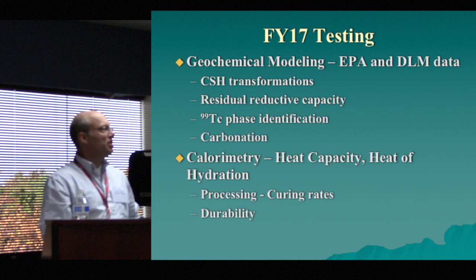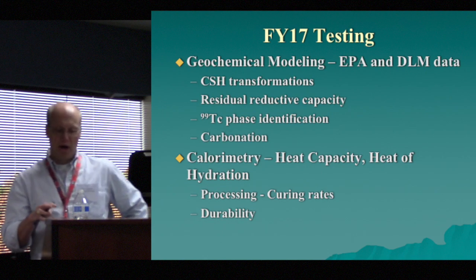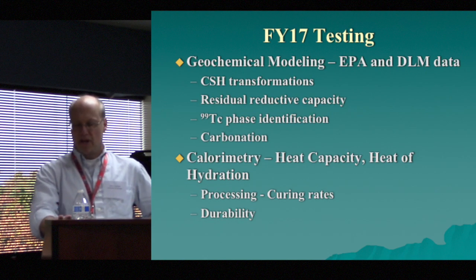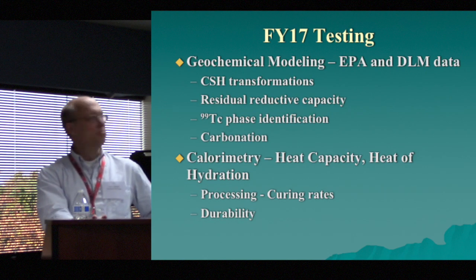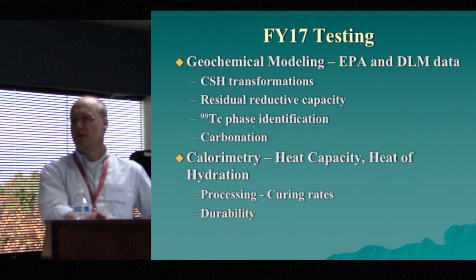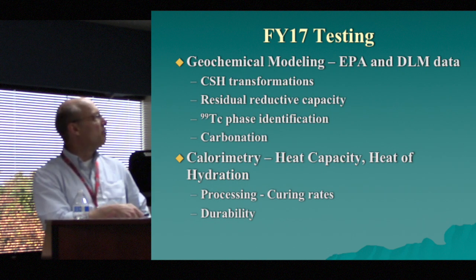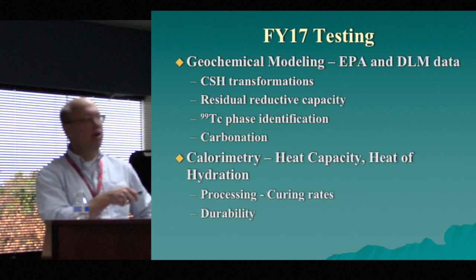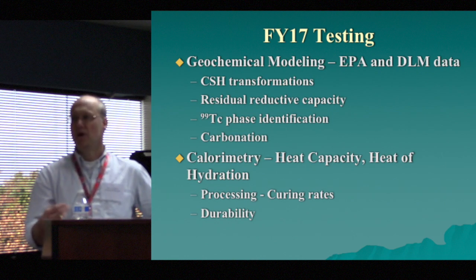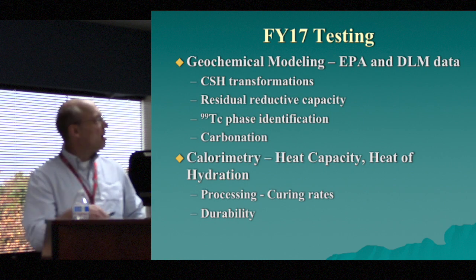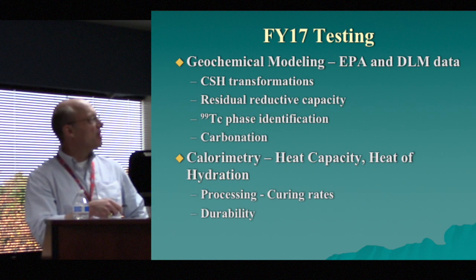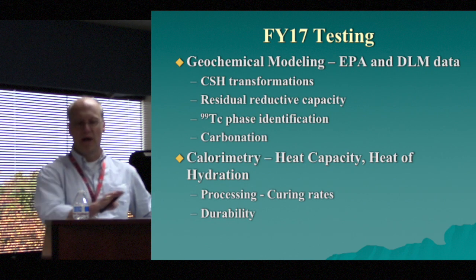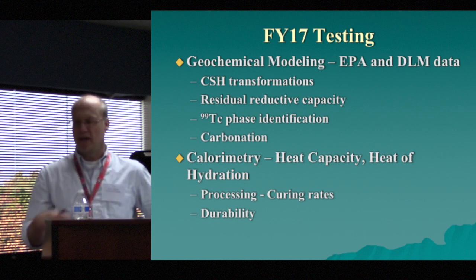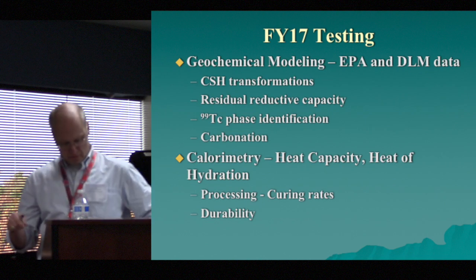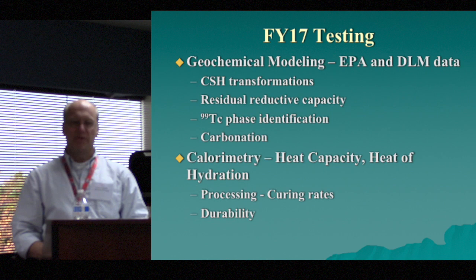And then we're also doing calorimetry on these materials because the chemistry is very, very different from simple Portland cement. And so that can have a big impact on the phases that are actually controlling the chemistry of the material. And we've even done some preliminary models, and it's very hard for us to use Portland cement as the controlling factor and get any of the calcium and the sodium and any of those things to come out as what we would expect. And I believe that's the last one.